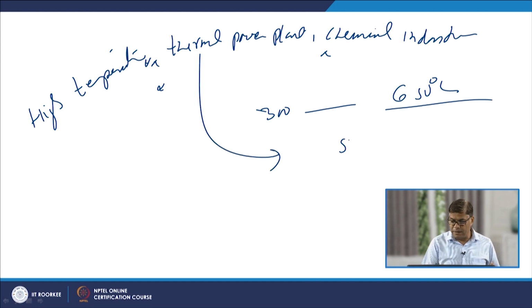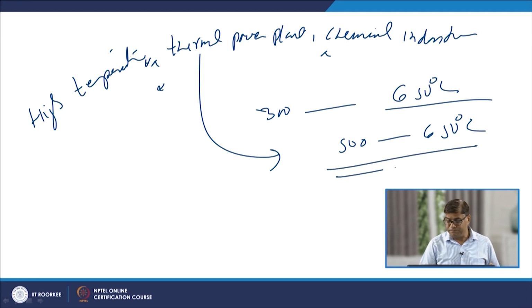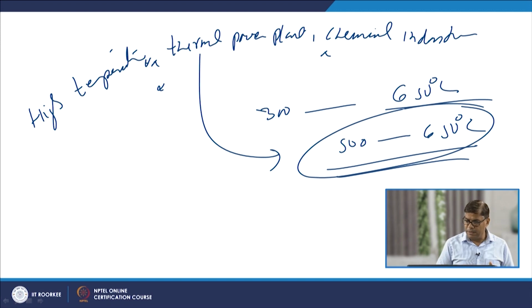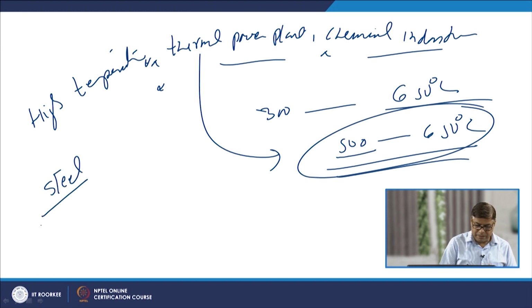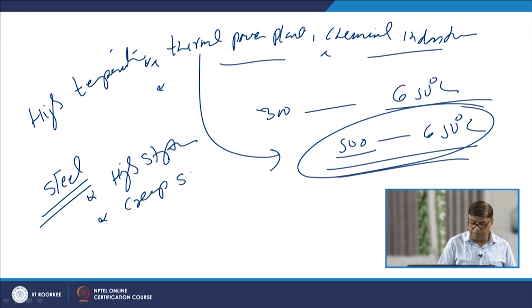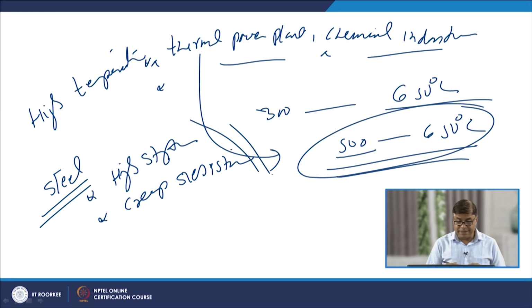So, in thermal power plants it is common to have 500 to 650 degrees centigrade, even nowadays 700 degrees centigrade temperatures are also used. So, the weld joints, whatever weld joints are needed to give the desired size and shape to the various components used in these thermal power plants, must survive at a higher temperature, in the range of 500 to 650 degrees centigrade. And so, we try to choose the steels which offer significantly high strength at elevated temperature, and they show good creep resistance. So, there is no change in dimensions as a function of time when the component is used at a higher temperature. So, high temperature strength and good creep resistance, these are the two important requirements for the components to be used at a higher temperature.